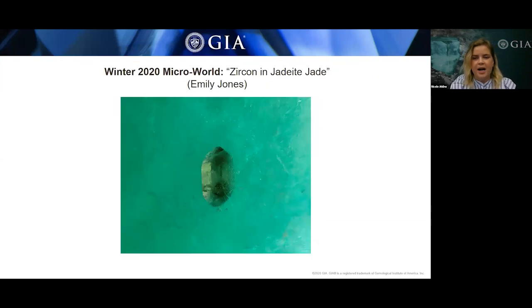So while examining a dyed and polymer impregnated jadeite jade bangle bracelet classified as B+C jade in the trade, this author noted a well-formed transparent brownish crystal inclusion. Raman analysis of the doubly terminated tetragonal prism revealed it to be a high zircon with little to no damage occurring to its physical and optical properties from metamictization. Although interstitial zircon grains are not uncommon in jadeite, euhedral crystal is rarely observed, and it is very surprising considering the various treatments that this host jadeite has undergone.